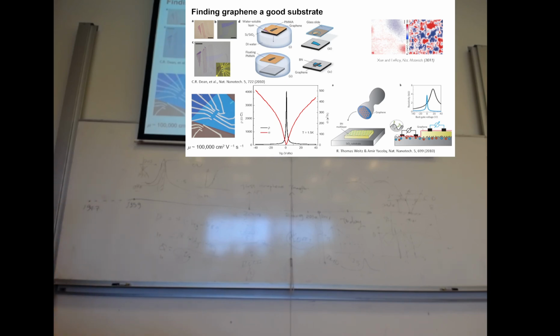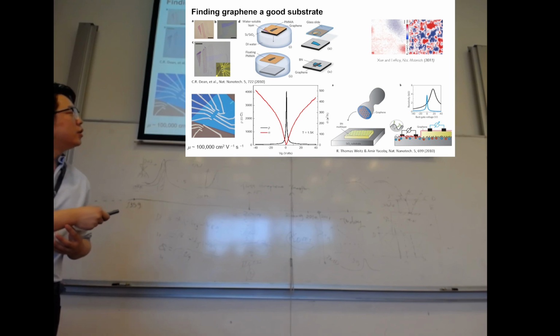And magically, you will see that this is also annealed, all right, okay, because there is only one surface supported by boron nitride. And then you will have this black curve as a field effect of graphene. And there you got a mobility of 100,000, which is already very good and comparable to suspended graphene, comparable to gallium arsenide quantum well. And there's a review paper talking about this, the mechanism behind.